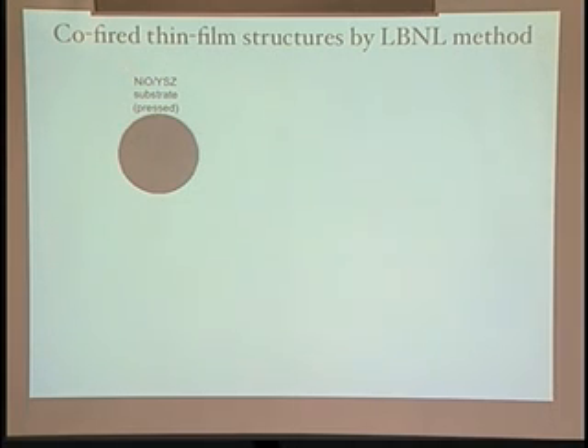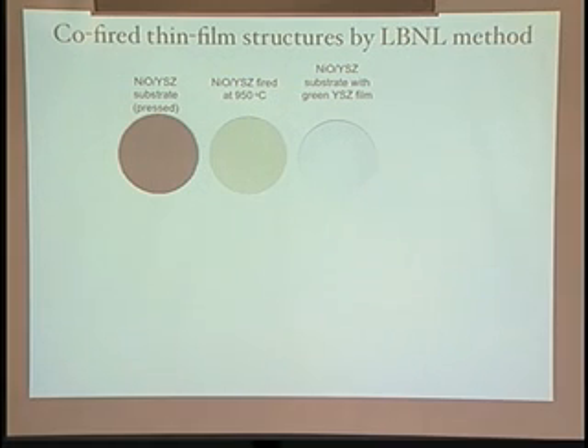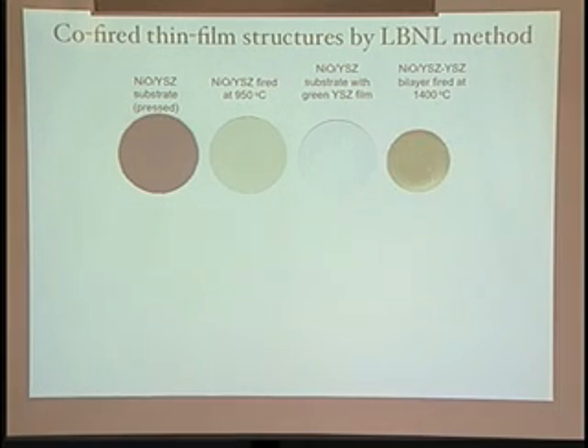So you start off with a very simple thing. You press this, make a tube. You can do all sorts of things. Okay, and we actually give it a pre-fire to give it some strength. And then, it's hard to see, just with an artist brush, but it's basically like a paint spray. We spray down a thin film of zirconia. And that is then fired, and what you see here is actually an SOFC.